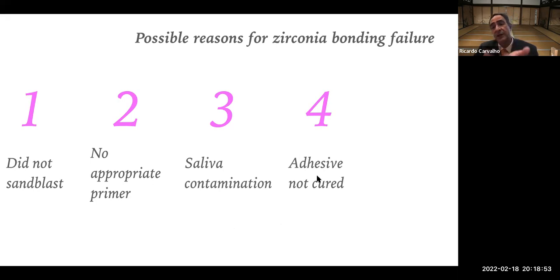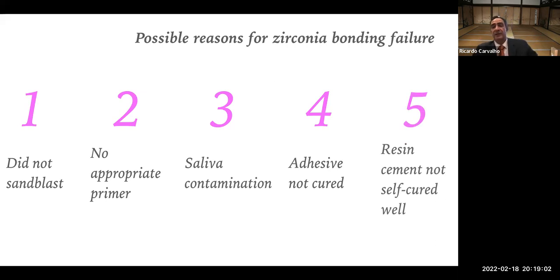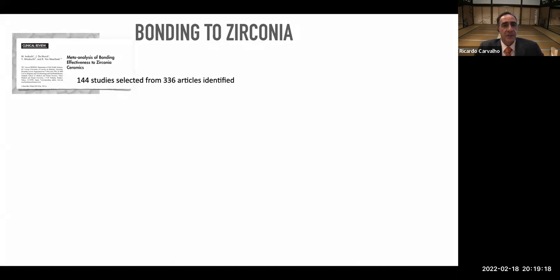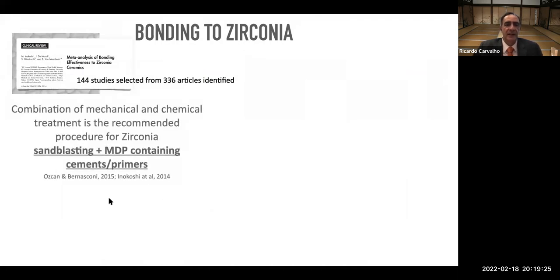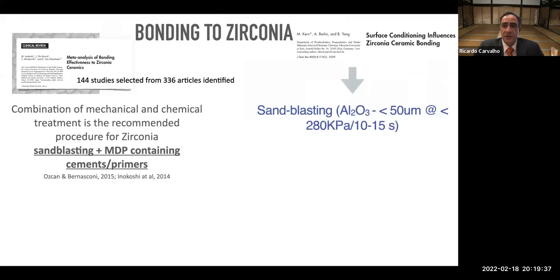Another reason is if you apply your adhesive after applying the primer, but you do not cure it, you need to stabilize that adhesive as well. And ultimately, you are utilizing a cement that is not a dual cure, and you do not accomplish a proper curing of the cement underneath your crown. When we go to the literature, for all these reviews, systematic reviews and meta-analyses, we found exactly these. The combination of this mechanical, which is the sandblasting, plus the chemical, which is the zirconia primer, seems to be the most reliable way to bond to zirconia.